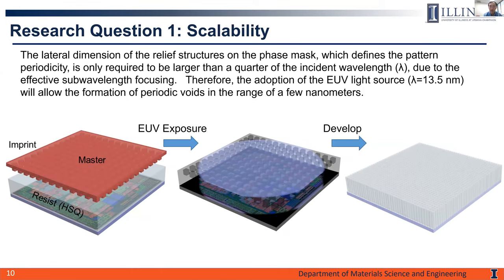And based on this preliminary data, the major question we want to answer in this project is what about the scalability of this proximity field nanopatterning? Right, so the pore size generated using the UV light, as we demonstrated in our previous work, is about several hundred nanometers. So these pores might be good enough as low-k dielectrics for chip packaging, but they're way too big for interconnects. By reducing the pattern periodicity and the wavelength of the incident light down to about 10 nanometers, the question is, will we be able to generate pores with size down to a few nanometers?